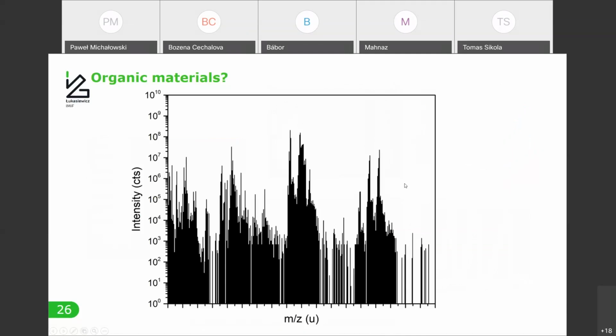Then I also wanted to show you the organic materials analysis. This is a very recent result. So magnetic sector SIMS is typically not well used for such materials. Usually you use TOF SIMS, but we made quite an interesting experiments using this high incident angle bombardment and ultra low impact energy.